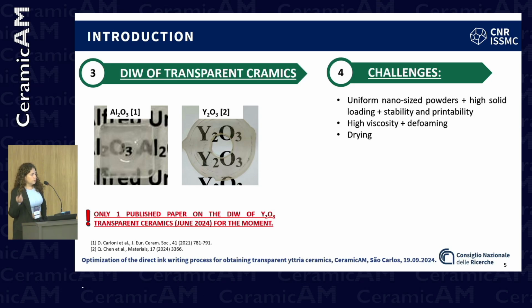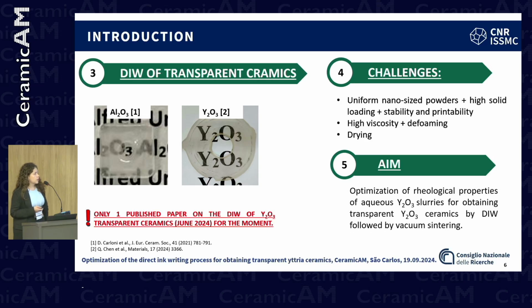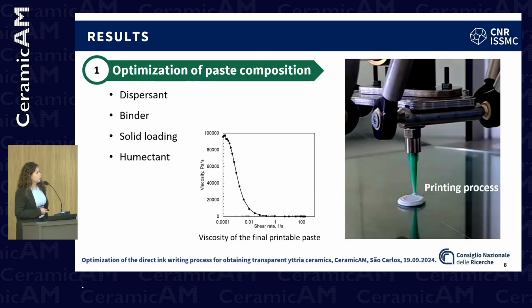Among the most important challenges is that we should obtain a stable and printable ink, having a high solid loading, and also uniform nano-sized powders. Together it's almost impossible. Also, high viscosity with defoaming and drying is very hard. So we should optimize the rheological properties of these slurries to obtain transparent yttria ceramics by vacuum sintering.